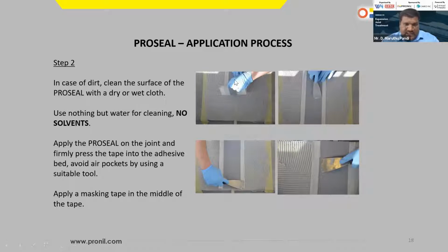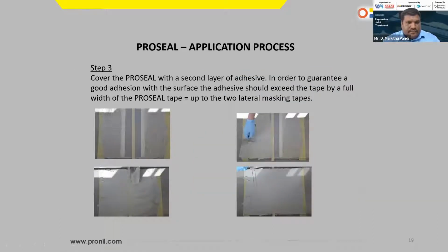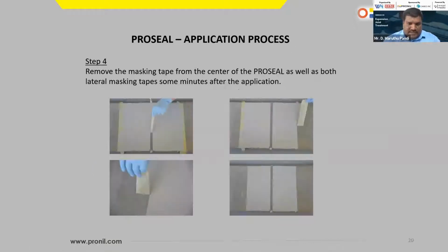Then apply the Pro-Seal tape on the center. Actually, this is a joint sealing tape, outdoor, having non-woven on both the sides. So this is also a TPE tape. And there is a masking tape which is applied on the center of the expansion joint. Why is this required? This is the area where the expansion contraction happens. So we are not supposed to put epoxy adhesive on the center of the joint. So we need the exact masking tape to be placed on top of it. Then he will be applying the epoxy adhesive on both the sides. Here you can see. Then at last, he will remove the center masking tape to accommodate the movements.